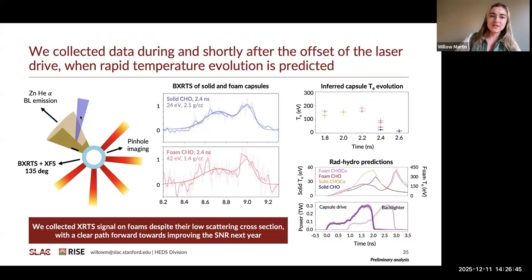We faced a lot of challenges in this experiment because our framing camera was broken for half of the day. But when we could collect data, we were able to simultaneously observe scattering signals and fluorescence signals, and we collected a data set that we're using to design the experiments that will follow up on this campaign in June of this coming year, where we'll once again study doped and undoped polymer foams using cobalt, as was used at LCLS, and iron as our underlying fluorescence surrogate material.